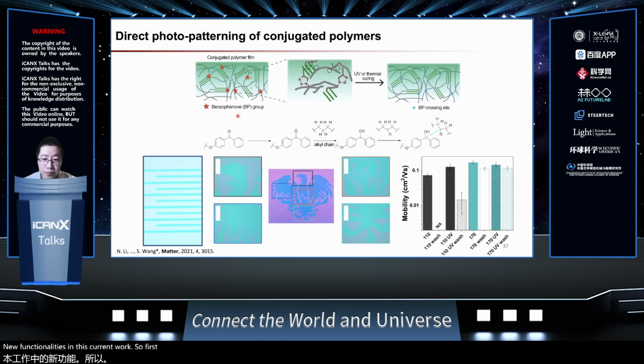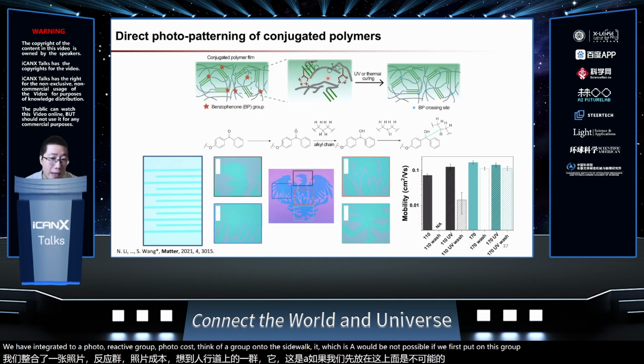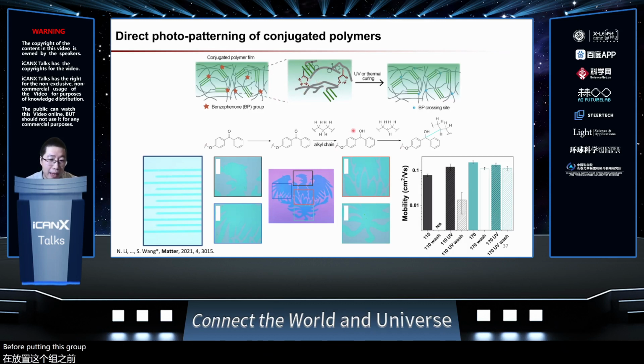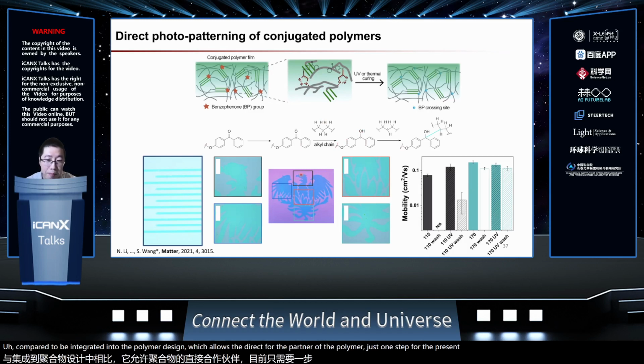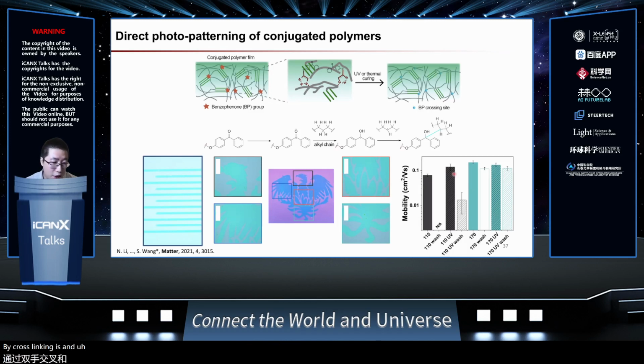So first, we have integrated a photoreactive, photo cross-linkable group onto the side chain, which would not be possible if we first put on this group and then finally polymerize, because this will react. But now, by putting this group in the last step, it can be compatibly integrated into the polymer design, which allows the direct photo patterning of the polymer, just one step photo patterning by cross-linking it, and still maintaining the unsacrificed performance when we use the solvent to dissolve the uncross-linked part.